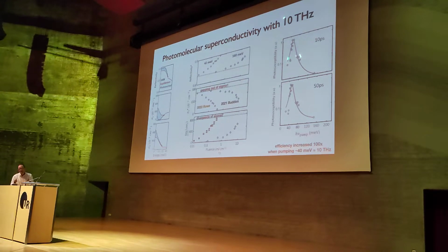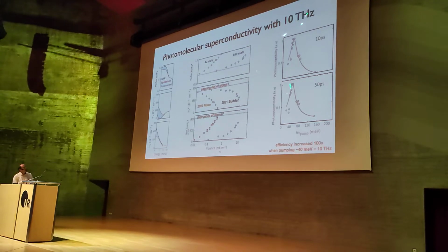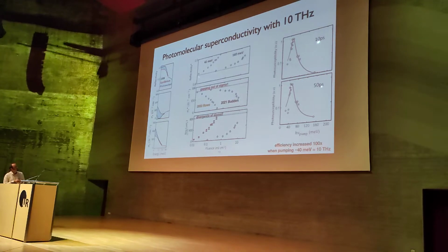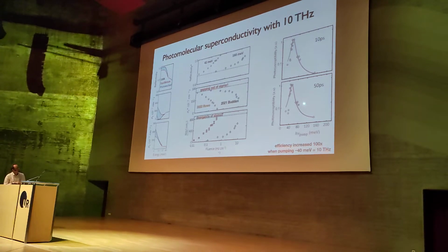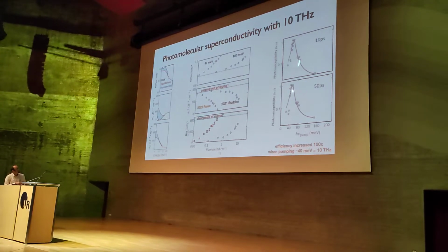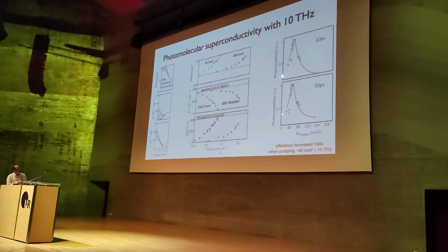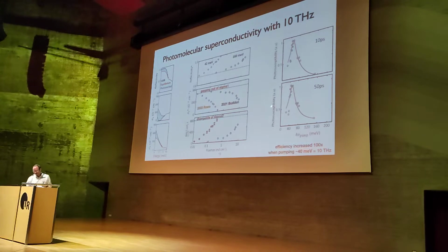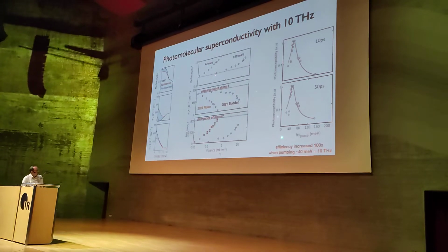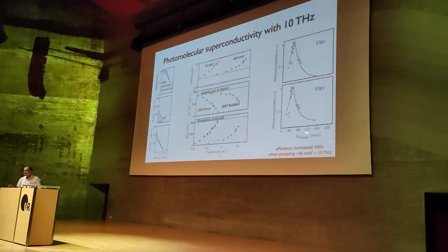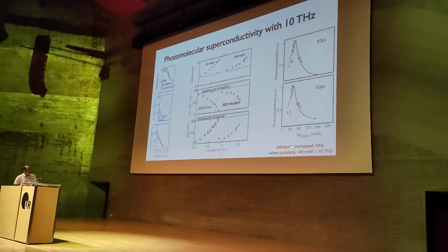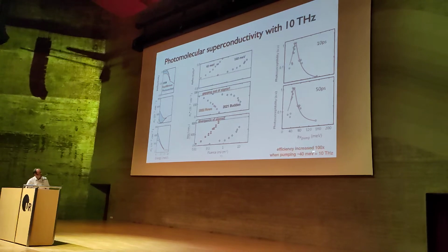So this is the terahertz magic that was announced in the title, and importantly, this effect still persists after 10 picoseconds. The compounds are much shorter lived than that, and still at 50 picoseconds you see it. Notice this is a log scale. So basically the efficiency is now increased by 100 times compared to what was published before for this 10 terahertz pulse.